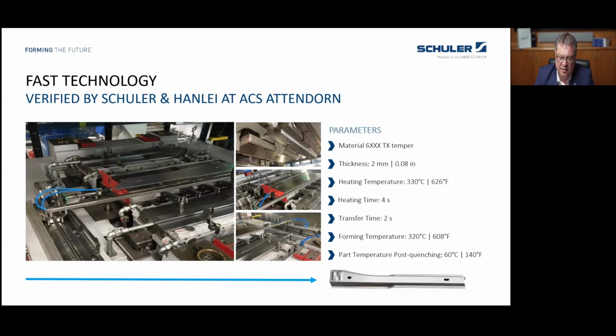And we used 6,000 series aluminum, and also with a special pre-treatment at the material supplier. So that's the reason why we call it TX temper and not T4 and not T6, because it's something in between. And this is also one parameter which can be adjusted to achieve the results you need for your parts. So the thickness of the blanks for the trials was 2 millimeter. The heating temperature of the heating plate was 330 degrees. The heating time was about 4 seconds.